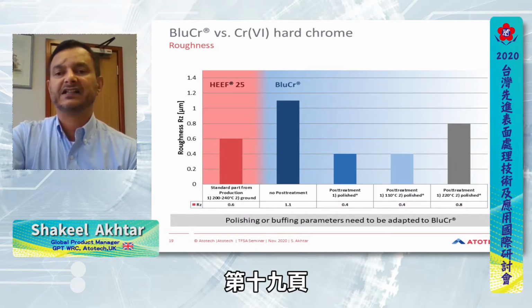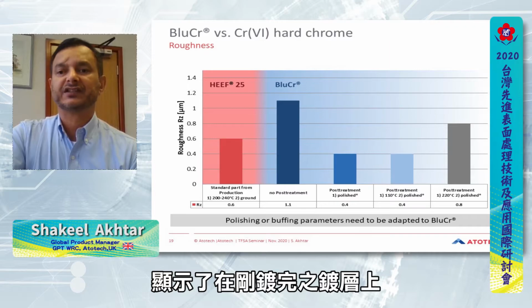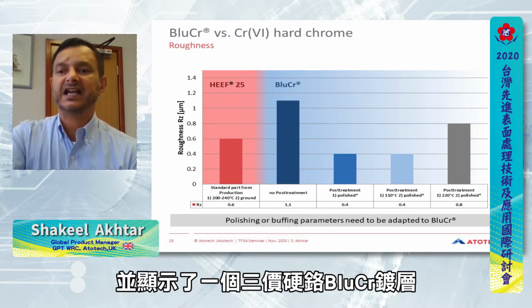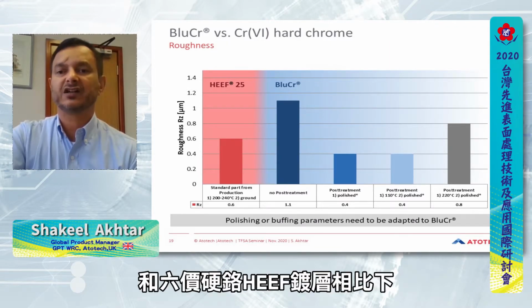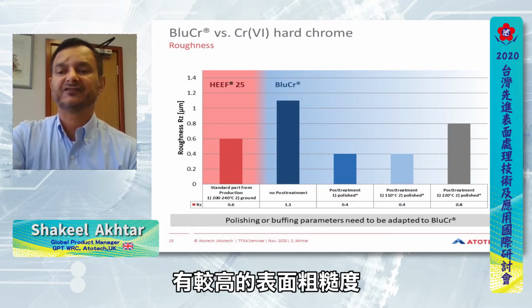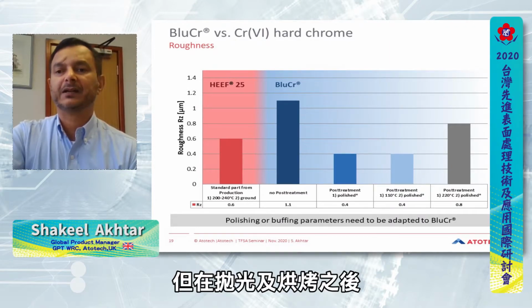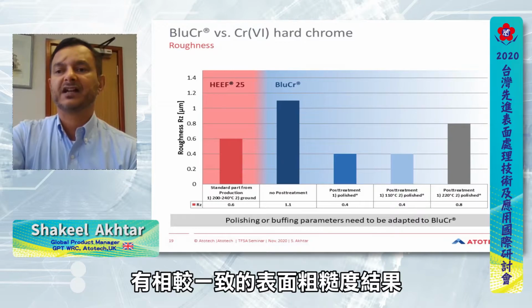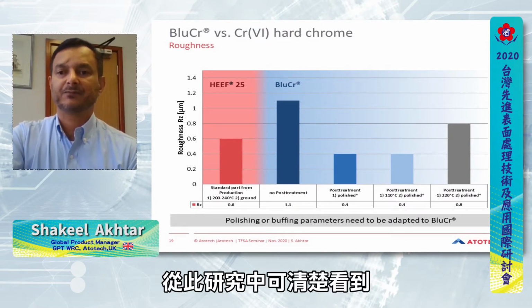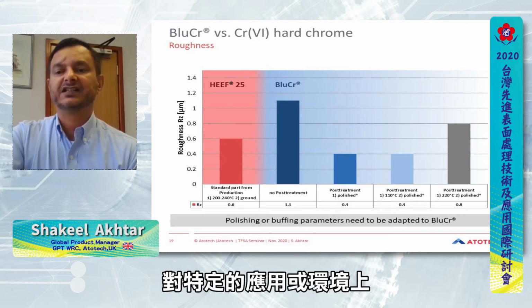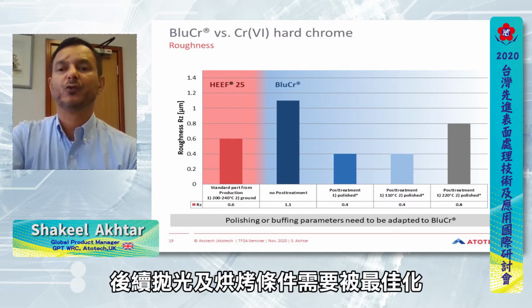hardness. In slide 19, this shows the roughness measurements on the as-plated deposit and shows a higher value than hexavalent chrome, but after polishing and baking, comparable results can be achieved. It is clear from this study that the polishing and baking conditions needed to be optimized for a given application or in a given environment.